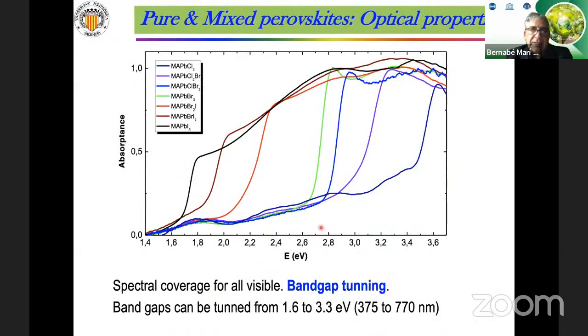Well, this slide shows the absorbance of the materials as a function of the composition. This is very interesting because it's quite easy to tune the band gap to the energy we are interested in. So this is the absorption as a function of energy. Here we have the low energy band gap, which is methylammonium lead iodide. High energy is methylammonium lead chloride. But we can tune the band gap by mixing the halides. So it's quite easy to obtain the desired band gap.